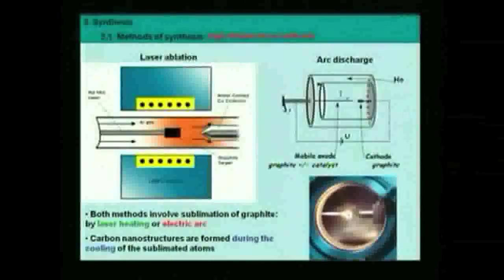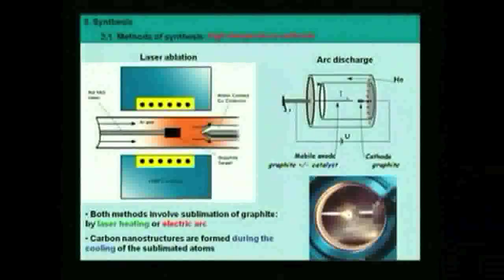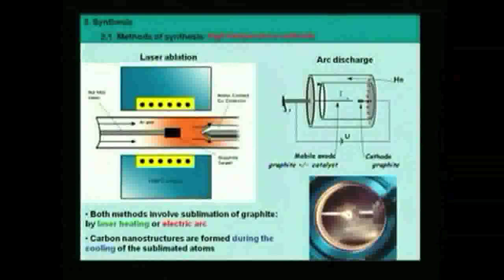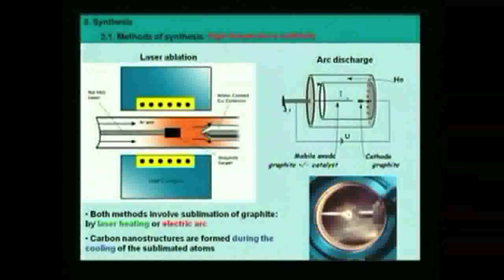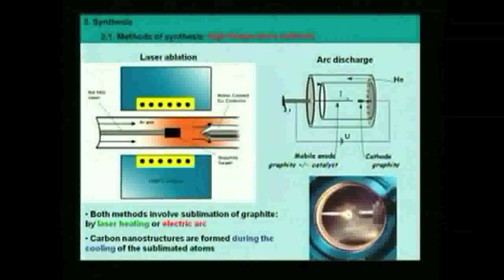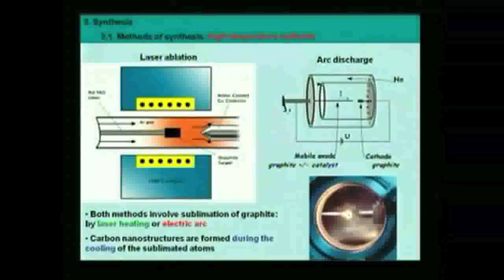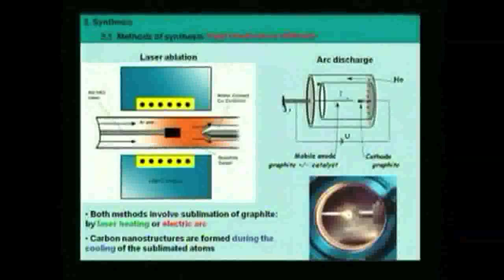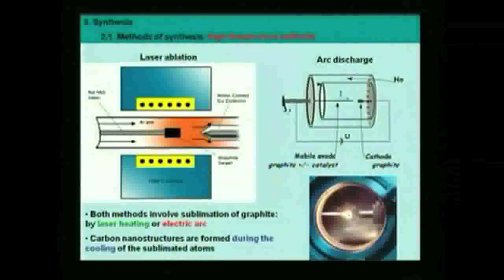Second technique is also a physical method. We will put helium in this reactor, and there are two electrodes facing each other, and we are going to apply a difference of potential between those two electrodes, and when the electrodes are close enough, then an electric arc will be created, and this will create a plasma that you can see here. And this plasma is at a very high temperature. What will happen is that this mobile anode will be consumed, just this one. The cathode will not be consumed because the plasma is oriented. There is a bombardment of ions from the cathode to the anode. It means that the anode is etched away, it is consumed, but the cathode remains the same.